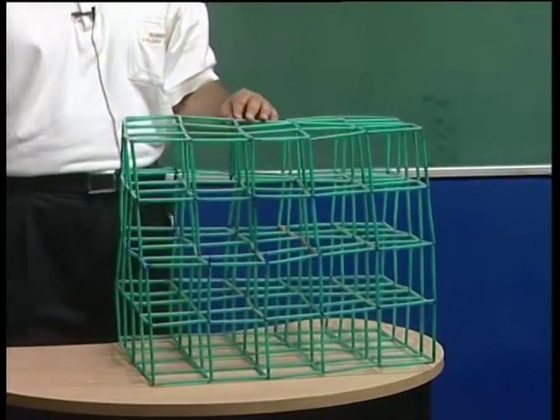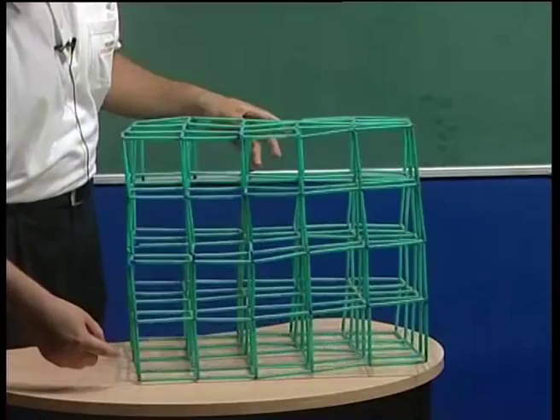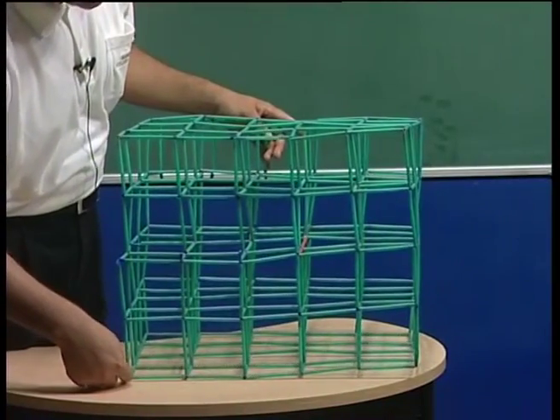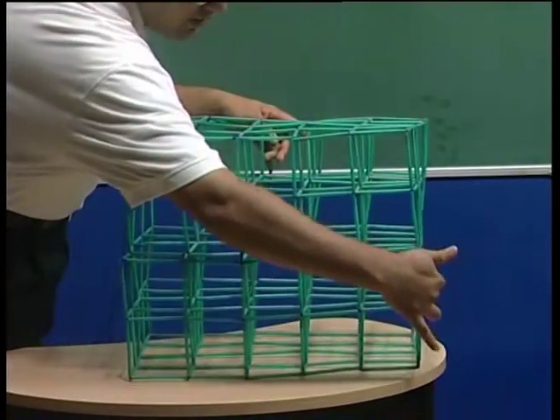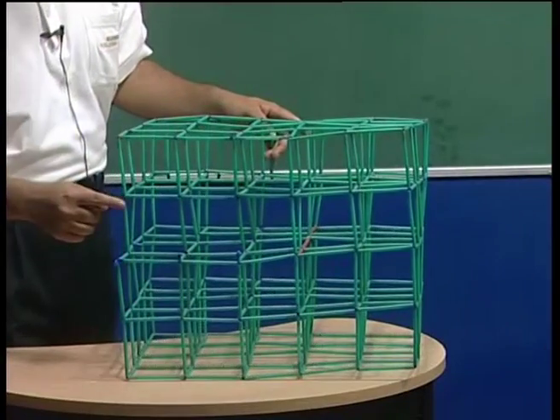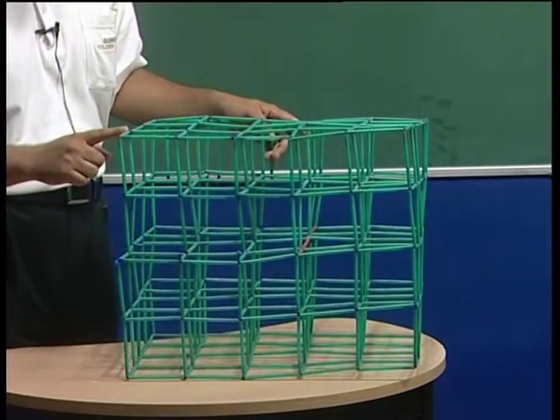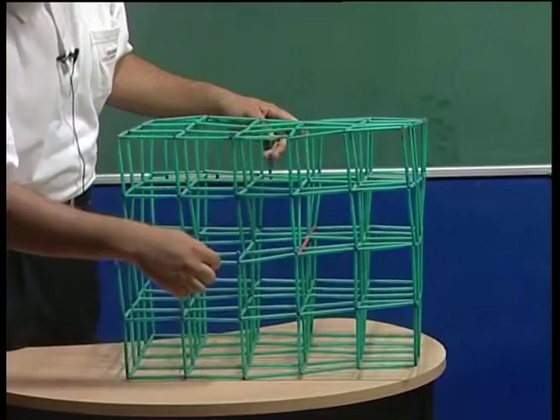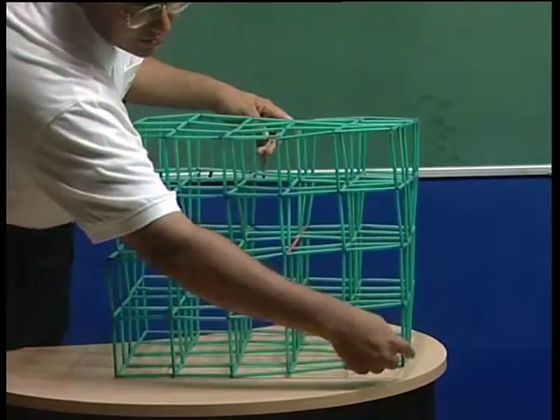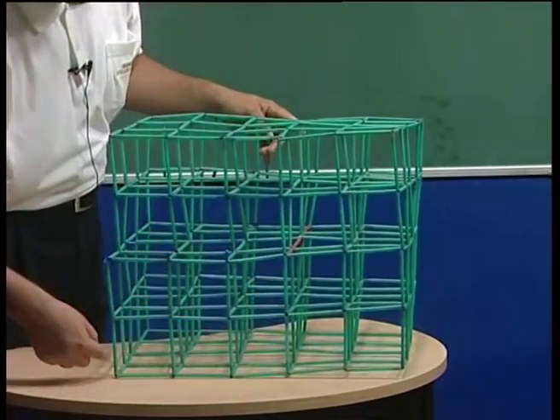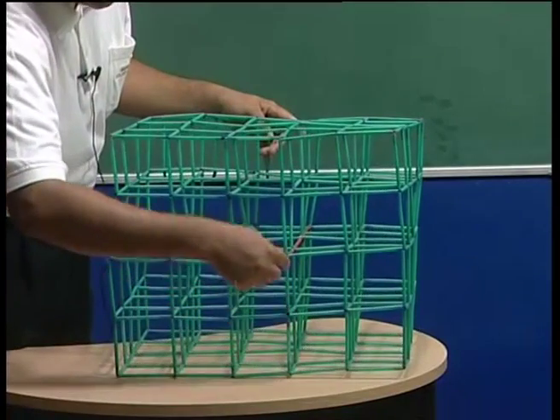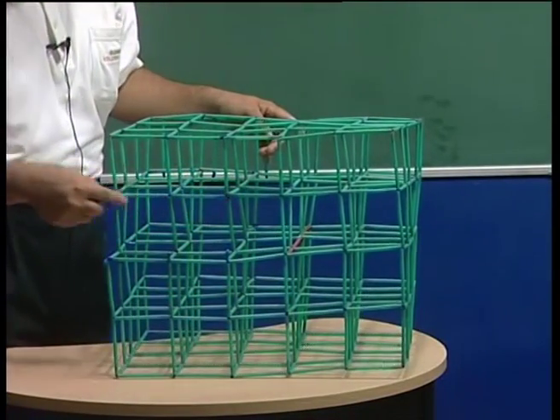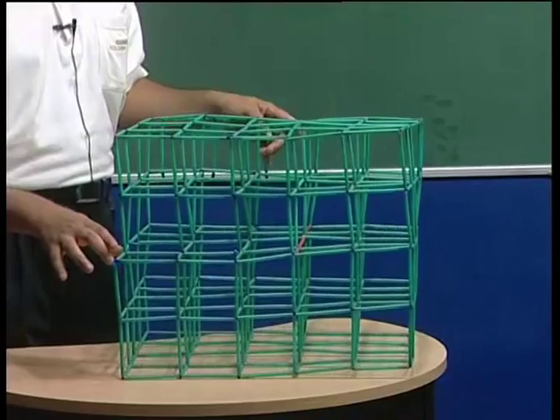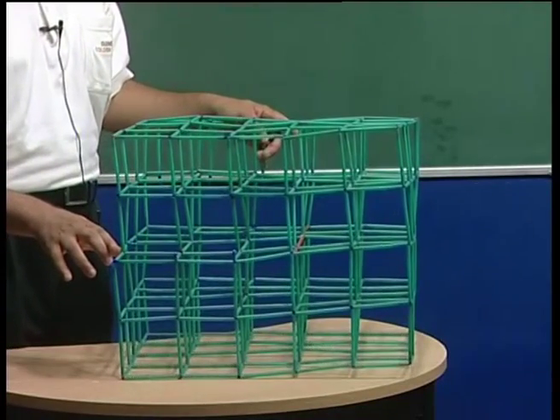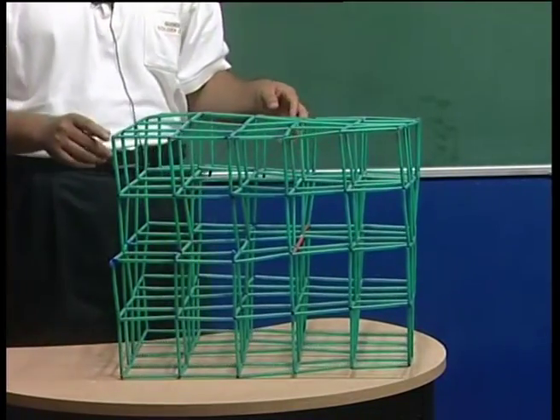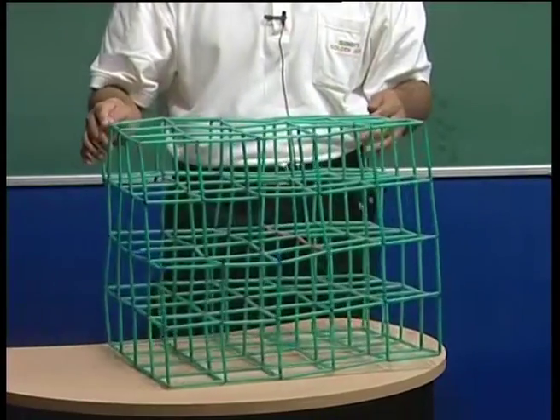Okay. And if I now travel along a particular plane, I would notice that I go like this, I go like this and I come back, I do not come back here, but I come back one step backwards. In a perfect crystal, of course, I go like this, like this, like this, I come back to the same place, but here if I go like this, like this, like this, and I shift myself, I land up here, one shifted, and this is my Burgers vector.